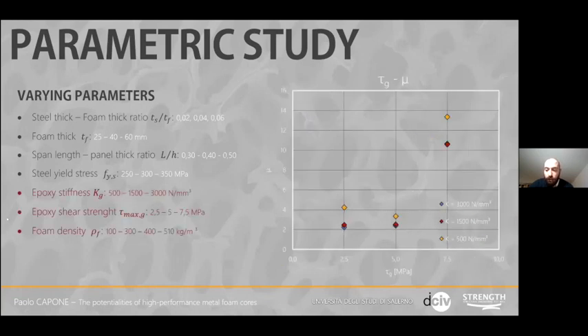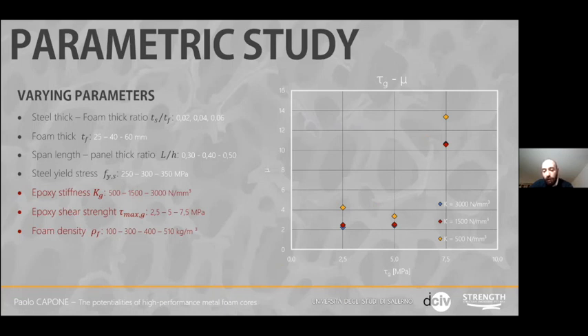The adhesive controls the ductility, and a high ductility can be obtained only if the adhesive is able to avoid the occurrence of local buckling phenomena. This objective can be achieved only by adopting adhesives with a high resistance. In our case, at least 7.5 megapascals.